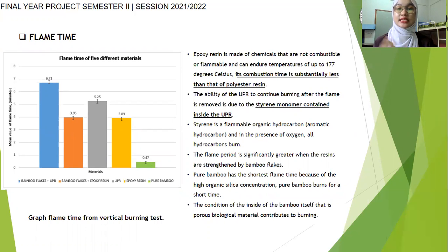Epoxy resin is made of chemicals that are not combustible or flammable and can endure temperature up to 177 degrees Celsius, and its combustion time is lesser than UPR. The ability of UPR to continue burning is because after the flame is removed, the styrene monomer contained inside the UPR itself is a flammable organic hydrocarbon and is burned in the presence of oxygen. The flame period is significantly greater when the resins are strengthened with the bamboo flake, as you can see from the table.